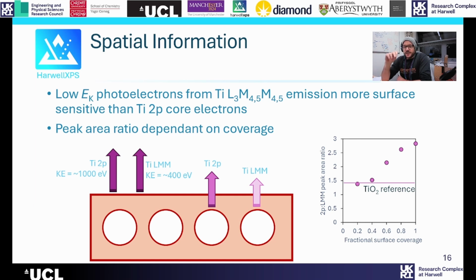But another way that we can investigate spatial locale is by looking at two photoemission peaks with different kinetic energies. Our Ti2p region has a reasonably high kinetic energy of around 1 kiloelectron volt. If we take our titanium LMM Auger emission by comparison, this has a kinetic energy of around 400 electron volts, which means the inelastic mean free path, and hence the information depth of these two emissions, is going to be different. And our titanium LMM Auger is going to be giving us a signal from closer to the surface.